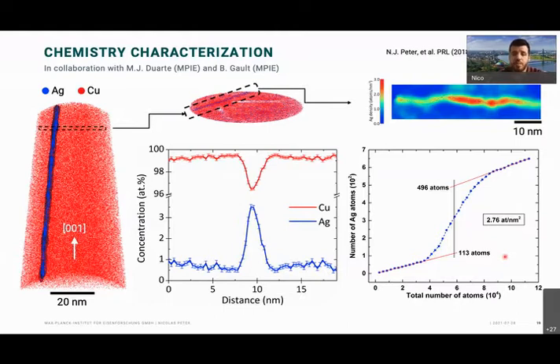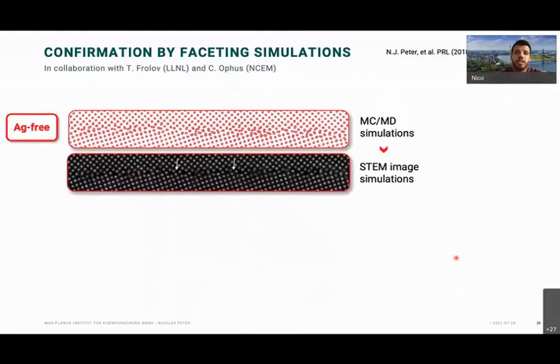So confirming this also. We then performed a little bit of MD simulations, actually Monte Carlo MD hybrid simulations, coupled with STEM image simulation now. So these are simulated STEM images. Can we reproduce this? Is this something we would think of in terms of theory? And indeed, we do get this. We have a little roughness associated to the boundary, but if we look at it, it looks very close to what we find in the experiment, which is nice because it confirms our experiment kind of, or in the other way around, we confirm the simulation now.